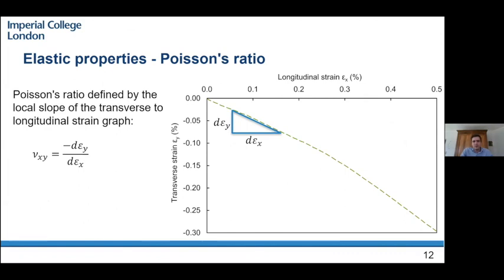Why Poisson's ratio? Well, the Poisson's ratio essentially gives us the lateral behavior of our material when it's stretched in its longitudinal direction. And we take, in our definition, the local slope of the transverse to the longitudinal strain graph. Because the model is really linear in the elastic range, we were able to represent the Poisson's ratios with a single value for our coupons.